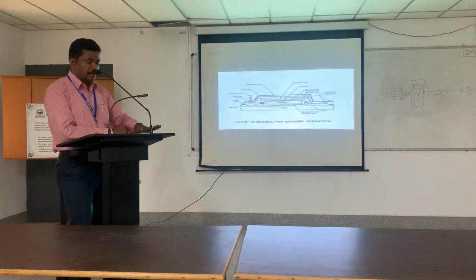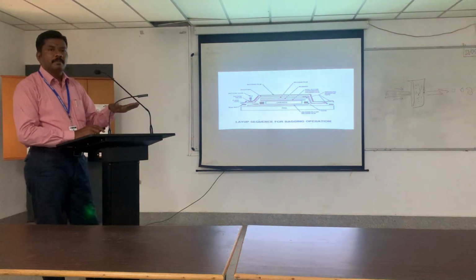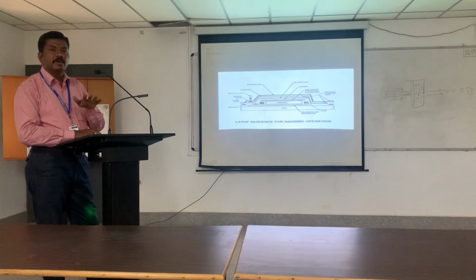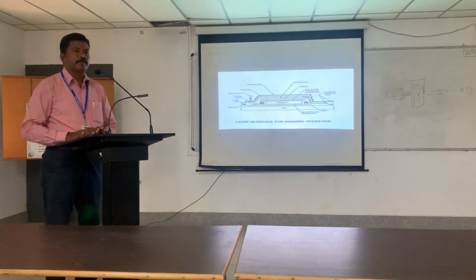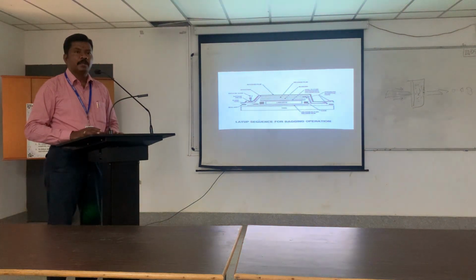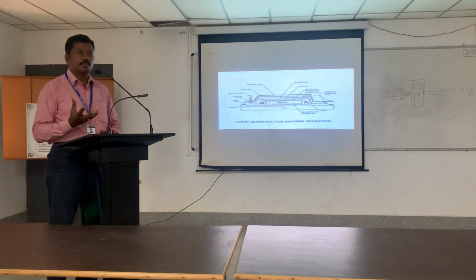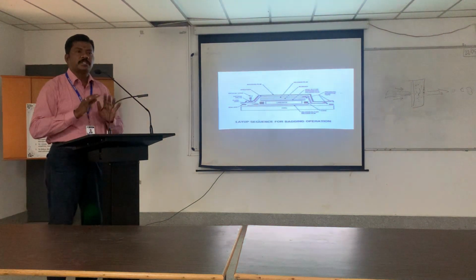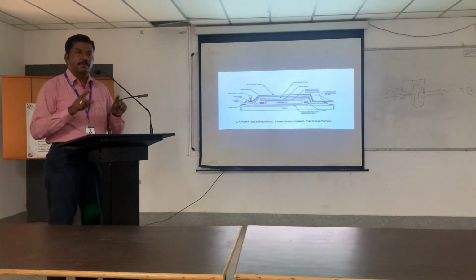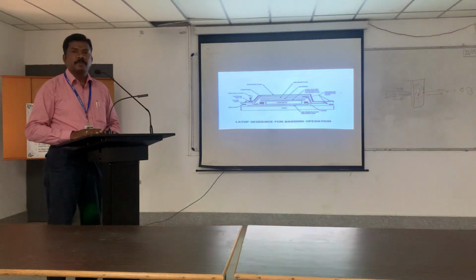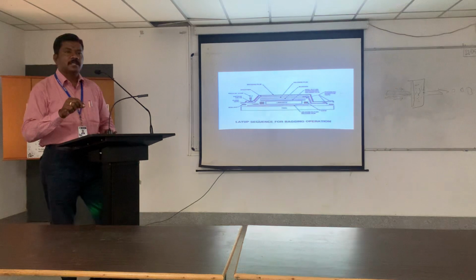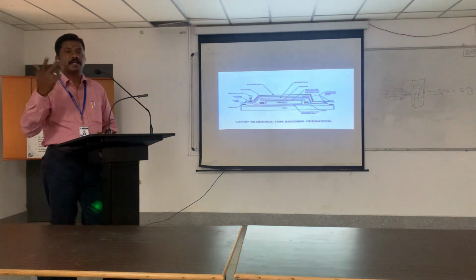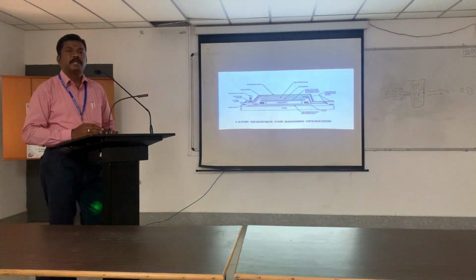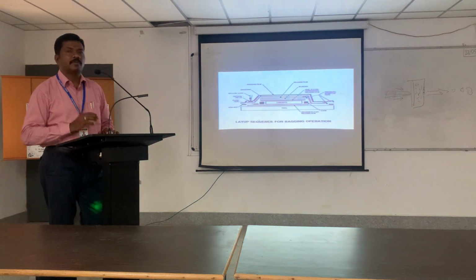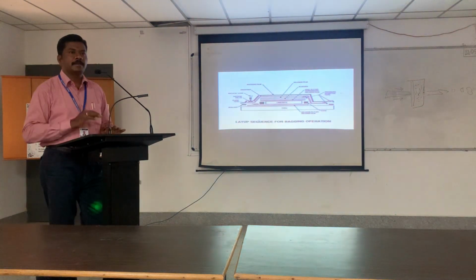Okay. First one is the bottom mold, then release film, then the laminate, covered with the dam material, beading material, on top of which is perforated release film, which will have bigger size holes, then on top of which bleeder film, which is like a cloth material that will absorb more amount of matrix, then on top of which again one more perforated release film, that is called the barrier film, which will again have holes smaller in size, higher in numbers. Okay. Then on top of which the breather film, which will absorb a small amount of matrix. Then on top of which the bagging film.